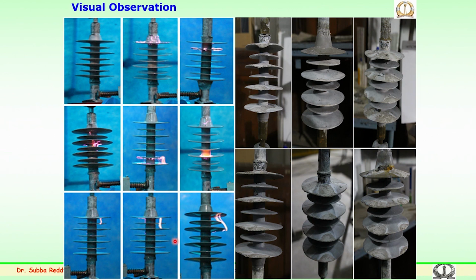So, this phenomenon, which undergoes 1000 hours of experimentation, after the experimentation we have seen the samples completely eroded, completely degraded. So, these are the samples for the AC conditions for normal contaminant and with the acidic composition with 2 different tanks.